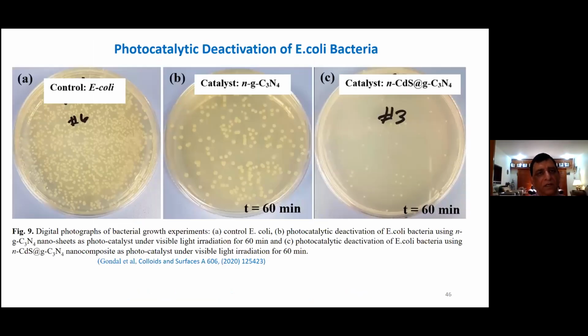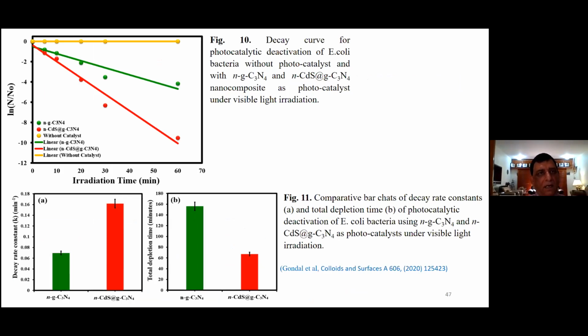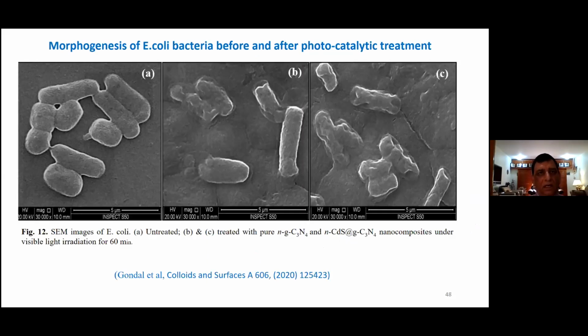And these are the plates which you see, that on the left you have control E. coli. And this is just pure graphitic carbon nitride. And when we have CdS and graphitic carbon nitride, we get very high killing of E. coli bacteria. And we can also calculate the reaction rate constant from there by plotting N over N0, where N0 is your initial concentration of E. coli, and N is the concentration versus different irradiation time.